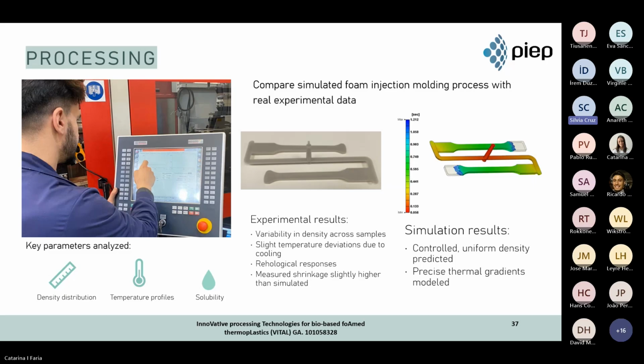In the experimental results, we observed some variability in density between samples and small temperature variations requiring some adjustments. In the simulation, we obtained a more uniform and controlled density, more defined thermal gradients, and a good estimate of the material behavior during the filling. In short, the simulation accurately represented the real behavior of the process, although some small differences were obtained,